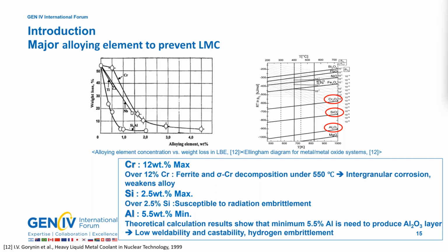First, chrome contents should not exceed 12%, as higher levels may cause intergranular corrosion and weaken the alloy. Second, silicon contents should not exceed 2.5%. If the silicon content is over 2.5%, the steel could become susceptible to radiation embrittlement.